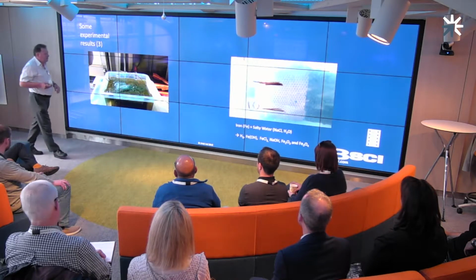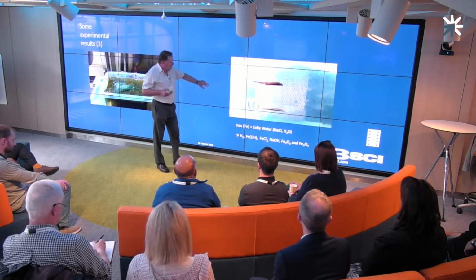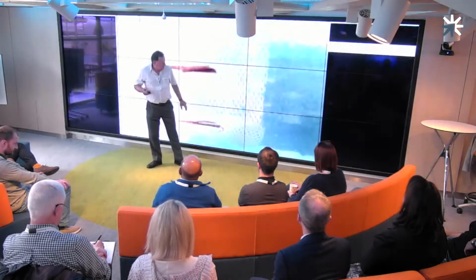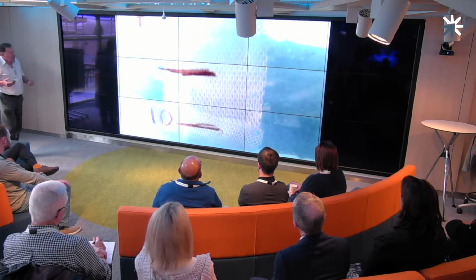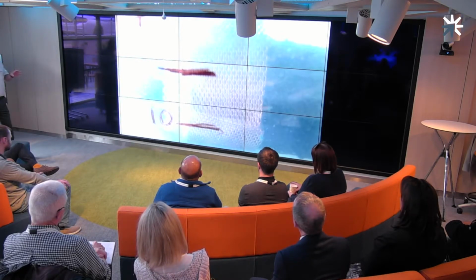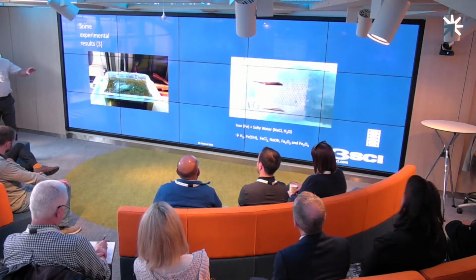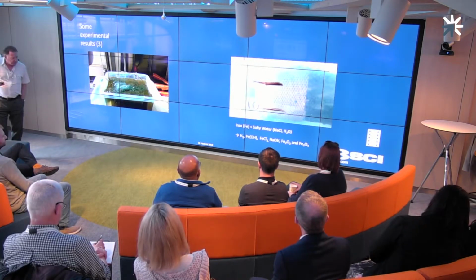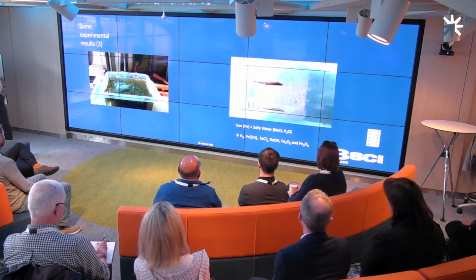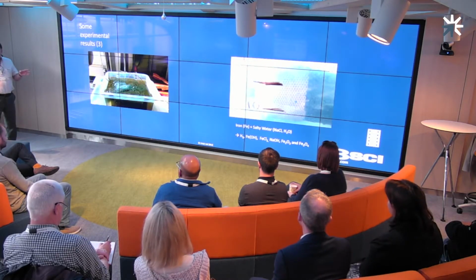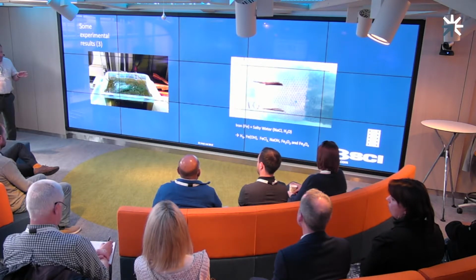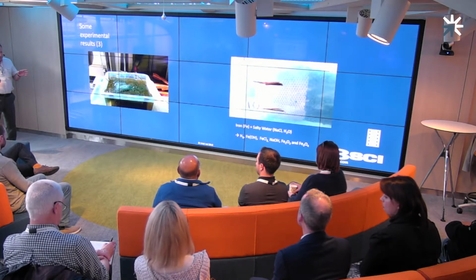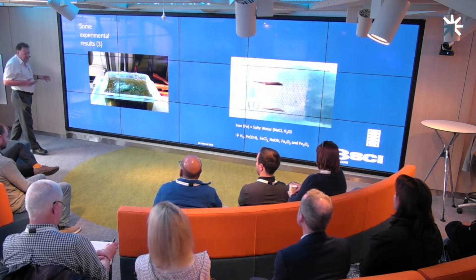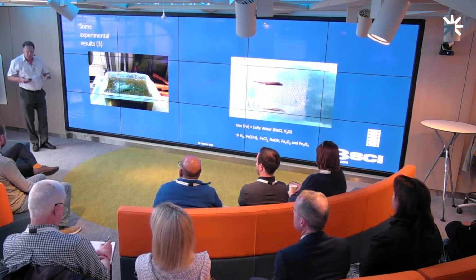And then what we have here is a couple of videos where I show what's going on when the electrical currents are flowing. So in this particular example, you can see in the background the copper pipe, but in the foreground you can see hydrogen gas being generated at the cathode in quite large quantities. When you look at the chemistry, which I've very loosely outlined in the writing at the bottom of the image here, you can see that hydrogen is a natural product of this accelerated corrosion process. And as we move forward and consider how we deploy this technology to larger and larger scales, capturing that hydrogen as a useful energy source could be very helpful to us.